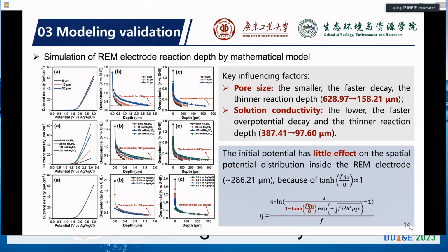That is, the potential rapidly declines to a certain value, and below that value, the reactions for pollutant removal no longer occur. The second very significant influencing factor is the solution conductivity. We found that the lower the solution conductivity, the faster the potential decay observed, also resulting in a thinner reaction depth. Interestingly, the initial potential has little effect on the spatial potential distribution inside the REM electrode, because this term is almost 1 within the overall potential we applied to the system.